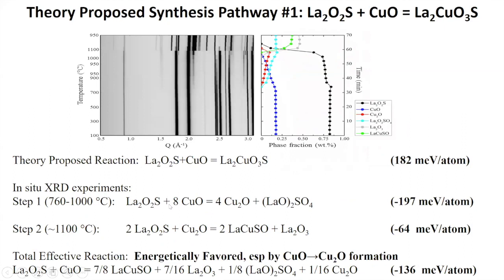Yeah, so I'm not gonna make it, but essentially what we find is that this step between copper oxide and the reduced version of copper, which is Cu2O, has a negative energy of 197 meV per atom, which tells us that reaction is very stable. And in fact, it dominates the total energy balance for this reaction.